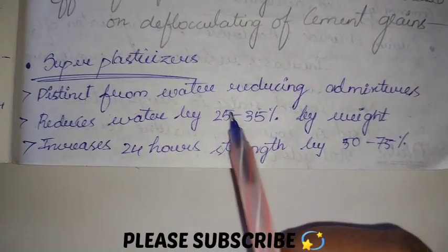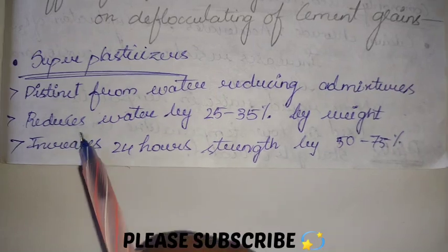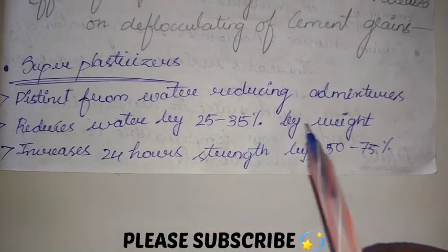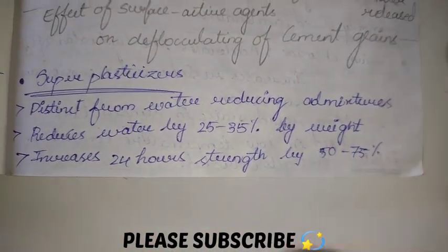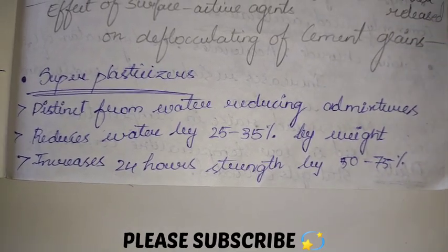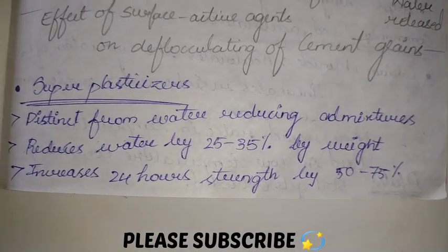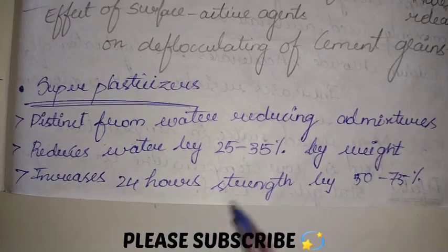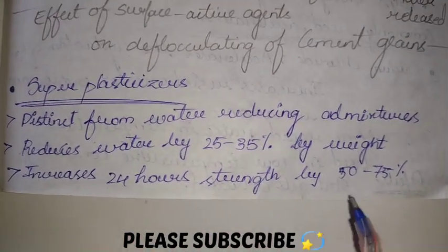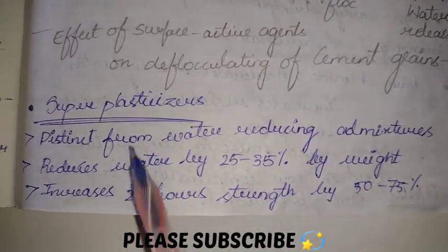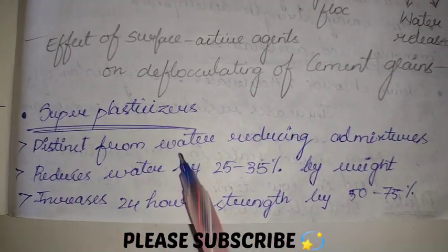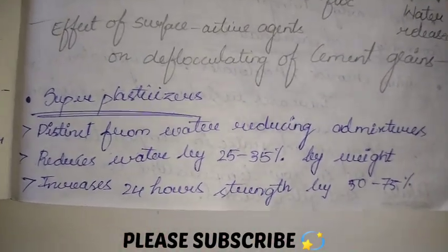Superplasticizers, distinct from water reducing admixtures, reduce water by 25 to 35% by weight. So whatever the weight of water is there, that can be reduced by 25 to 35%, and they increase 24-hour strength by 50 to 75%. So because of the addition of superplasticizers, we are increasing the early strength of the concrete.